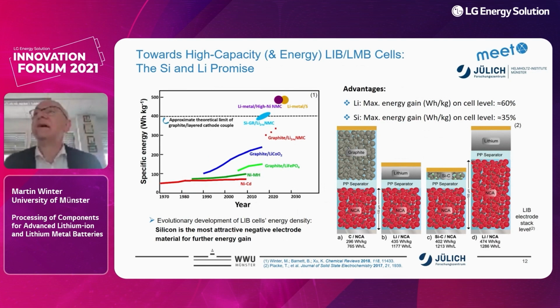compared to silicon. And also you can simply increase, in a given volume, the cathode thickness if you are able to create such a cathode, which is of relatively large thickness of more than 165 microns, and a lithium metal anode. So at the end you get energy gains with lithium of up to 60%, and on silicon even 35%. And this is basically related to capacity. A little bit on the lithium side also to voltage, but mainly to capacity. So higher capacity gives us higher energy. This is the motivation for these materials.